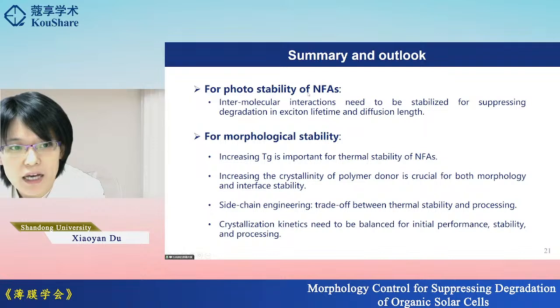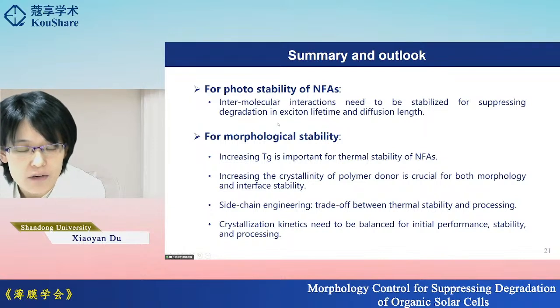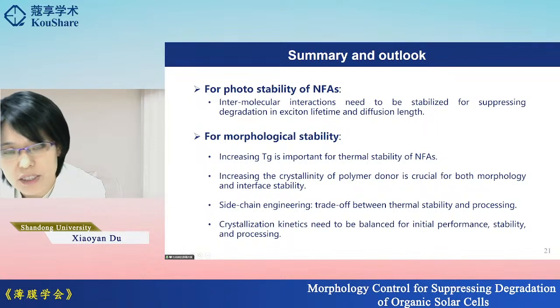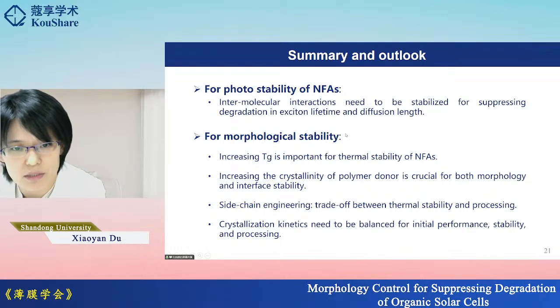Okay, now I come to the summary. For the photostability of non-fullerene acceptors, we show that the intermolecular interactions in the aggregated states need to be stabilized. And this degradation in the intermolecular interaction will strongly affect the exciton lifetime and diffusion length. This also highlights the importance of faster exciton dissociation for the photostability of the non-fullerene acceptor materials.